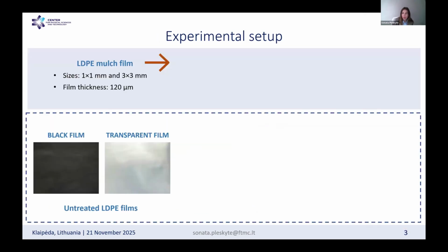So as a prototype for microplastics, we used commercially available LDPE films, which we bought very simply in a local supermarket. And we found LDPE mulch films in two colors. It was a black one and also a transparent one. Also, we cut these films into two size groups. The first size group was 1 by 1 millimeter, and the second size group was 3 by 3 millimeters.